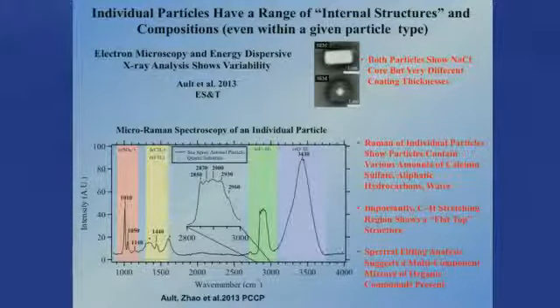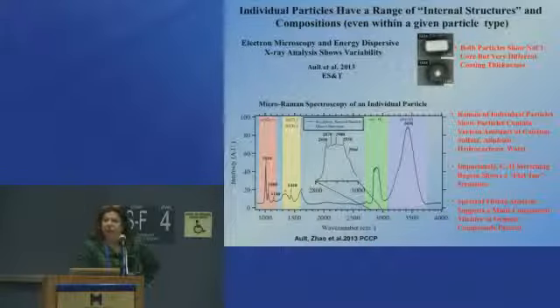Another thing that we learned is that individual particles have a range of internal structures. These two particles have sodium chloride at the core. This one might be pure sodium chloride, but maybe it has a little ring of organic material around it. But then here we have another particle, almost the same size, with a very small sodium chloride core and a much thicker organic coating. How will these behave in the atmosphere with respect to heterogeneous chemistry, their optical properties, how they nucleate clouds? It's not going to be the same, we think. So those are some of the questions that we're asking in the center.